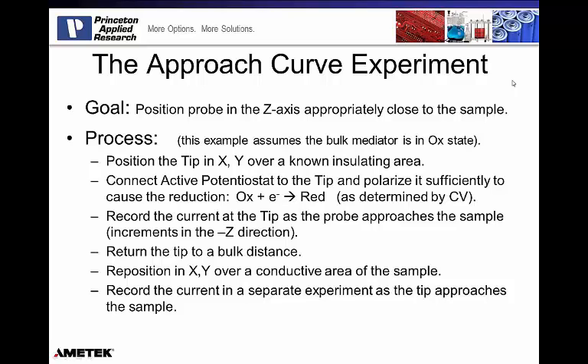If you started with a bulk mediator in the reduced state, or started with ferrocene in the iron 2+, you just swap which potentials you're going to be applying. So the first step in the process, I'm going to position the tip or the probe in X and Y over a known insulating area. Then I'm going to connect the active potentiostat, or the potentiostat where I'm making the measurement, to the tip. I'm going to polarize it sufficiently to cause the reduction reaction, ox plus an electron going to red. Again, that's determined from the cyclic voltammetry experiment.